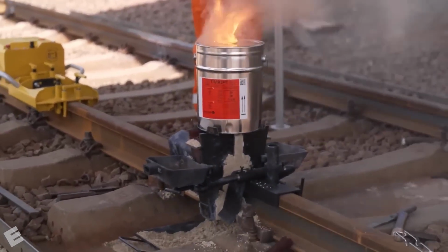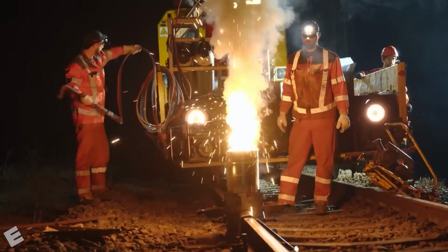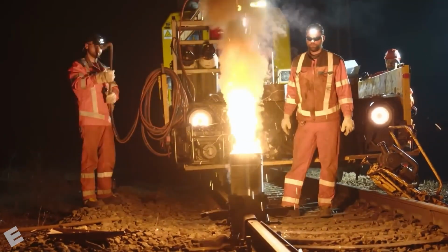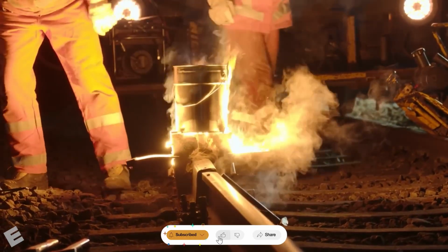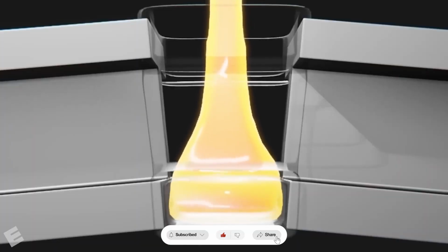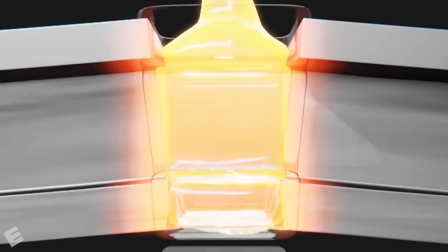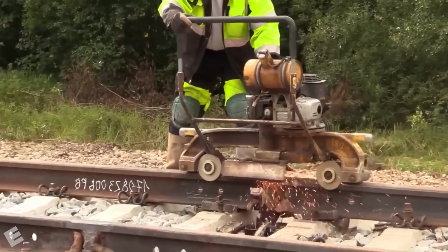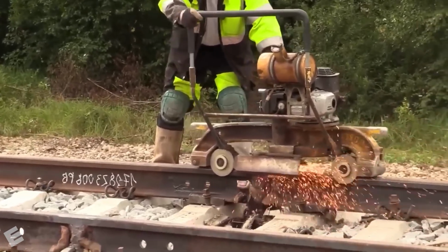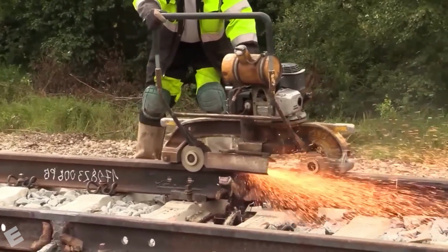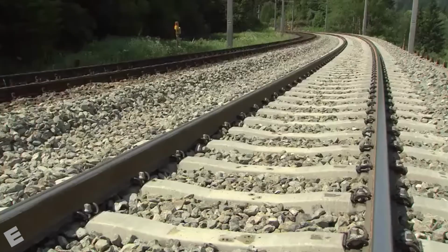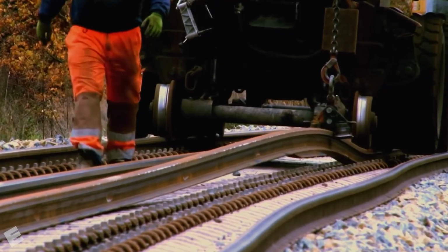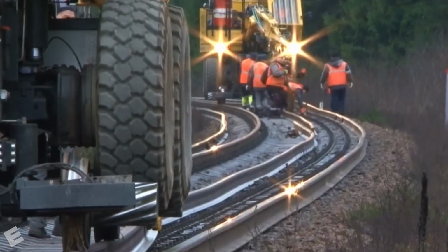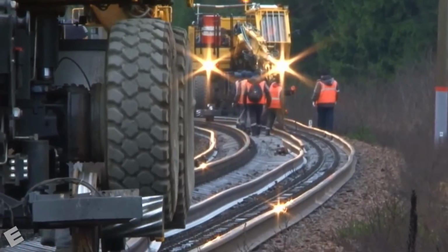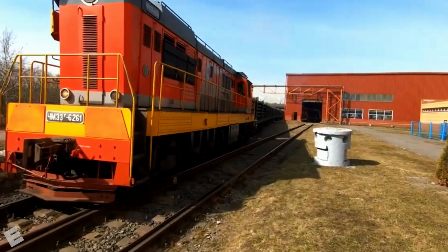When the mixture is ignited, aluminum removes oxygen from the iron oxide in an extremely hot chemical reaction. The reaction produces molten steel and aluminum oxide slag. The molten steel flows into the mold, fills the gap, and fuses with the heated rail ends. After the joint solidifies, the mold is removed. Excess metal is sheared away, and grinding machines restore the exact shape of the railhead. When finished correctly, the wheels pass across the weld without striking a step or gap.